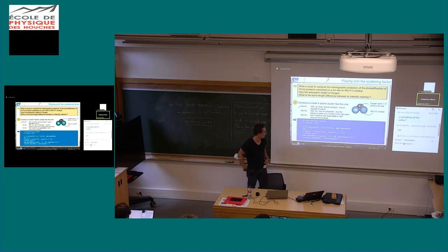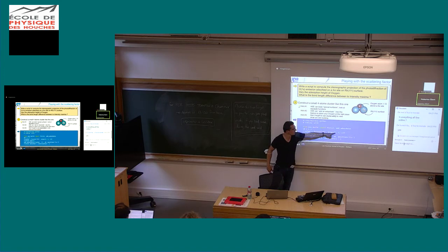So how to create the cluster? This time, there is no need to use the hemispherical cluster function like for the copper example. Because this is only 3 atoms, you can just use the FCC111 function from ASE, and you have to specify the size, the repetition, so the size of your surface. So 2 atoms along the first vector x, 2 along y, and 1 along z.